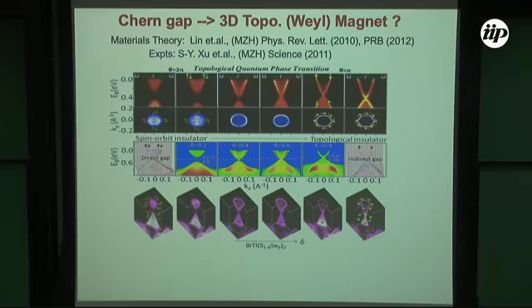So the experimental goal is to detect that state. What is the critical point? Why is this interesting? Because at that point there's a 3D Dirac cone in the bulk, because that's where the band is inverting, right? So we can trace that spectroscopically. This set of images is better. When you have a trivial band insulator, we see a direct gap. On the other end, after the band inversion, we see an indirect gap. And in between, as we increase selenium concentration, at some point we see there is a gap closing. And then by looking at the kz dependence, kx, ky, kz, we tell whether it's a 3D Dirac cone or not.